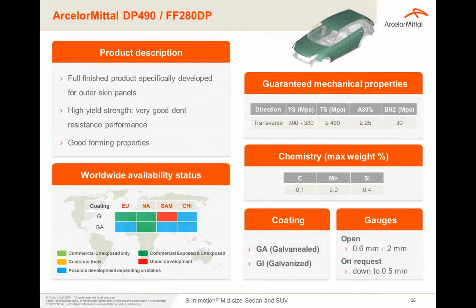ArcelorMittal Dual Phase 490 is a fully finished product specifically developed for outer skin panels. The high yield strengths, as described in the table on the right, provide very good dent resistance performance. As you can also see in the table, the very high elongation provides good forming properties as well. The product is available in GI in Europe and both GI and GA in North America. Development in GI is ongoing in South America and could be done also in China, depending on the market request. The feasibility is open down to 0.6, but as I already mentioned, we also processed some coils down to 0.5 with very good exposed quality.